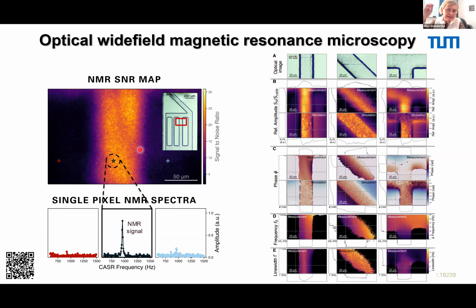And is it radiation to this 10 micron depth? Because probably it's huge damage, with the high power required to implant nitrogen atoms at such depth. No, this is grown. This is grown with nitrogen. Exactly, so overgrown and then basically irradiated with electrons. Okay. And now I forgot the second question.